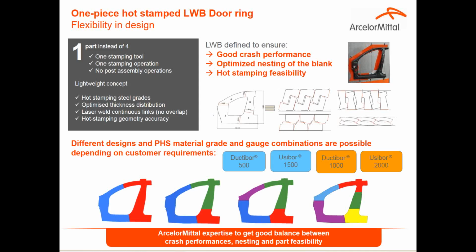With the introduction of the second generation of press hardened steels, what we see is now the advantage of not only iterating on the number of weld seams and locations of the seams, but also iterating for the strength combinations. So you can see, as illustrated in the pictures below, that you can combine these different materials together to come up with both grade and gauge combination for the highest level of material utilization for the side structure.